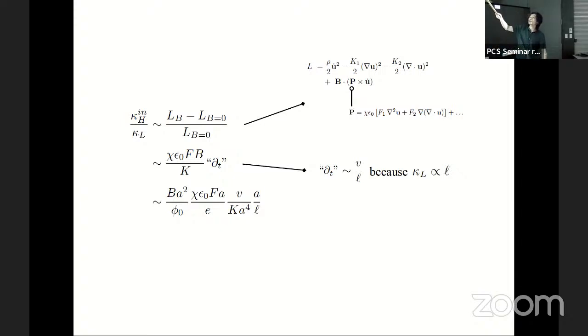And the time reversal even part of the Lagrangian is this usual terms of the phonon, and the time reversal odd part is this. And if you take the ratio, you will find the ratio looks like this, where you have a time derivative because there's a u dot here. And how do you estimate the time derivative? It turns out that time derivative should be estimated as v over the mean free path L. Why is that? Because the intrinsic Berry phase effect should be independent of the mean free path. But the longitudinal transport, as we know, should be proportional to the mean free path. So this partial T will be estimated by the phonon velocity versus the mean free path.